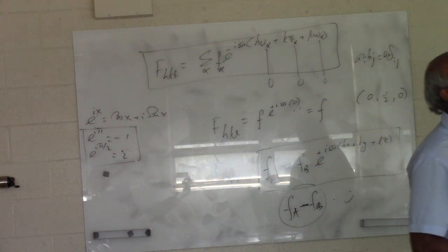So that means, just like FCC, it has to be all even, or if it is all odd, you get reflections only if they are non-equal. So that's the thing to remember. You can have all odd, like here. If they are the same, you don't get this one, right? 1, 1, 1, you never get, then 3, 1, 1, you never get. But if they are all even, you always get those numbers, right? So please remember this one.